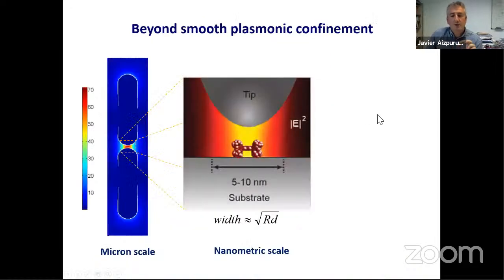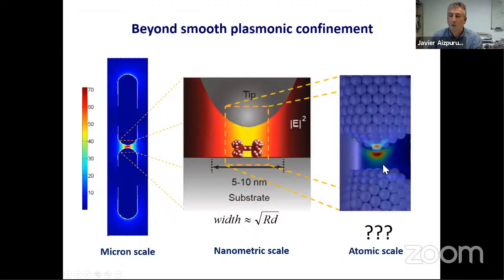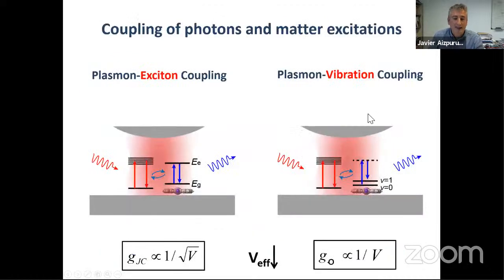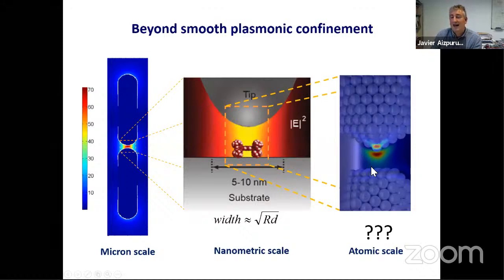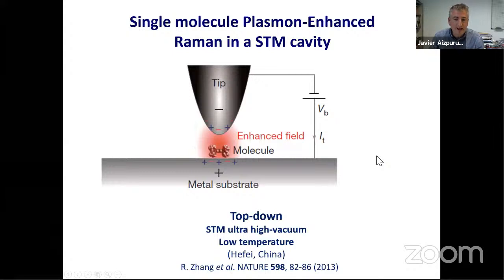One more thing, and 5 more minutes before we make a little short break for some questions, is we can go beyond this description of a smooth Gaussian, or even classical or Gaussian quantum description, and start paying attention even at the smaller scale, not just at 5, 10, 20 nanometers, but really going to the atom and try to see what happens with the electrons, with the conduction electrons and so on at this scale. And why is this interesting? Well, again, because if we want to boost and increase the signal from excitons and vibrations of molecules, the interaction and the signal scales with the inverse of the effective mode volume. If we manage to trap the photons at the tiniest effective mode volume, we will improve this interaction at the optimal level, right? And I show you an example of this.